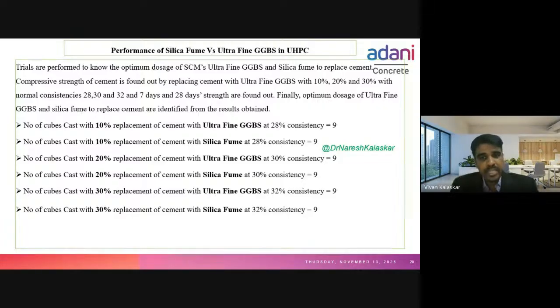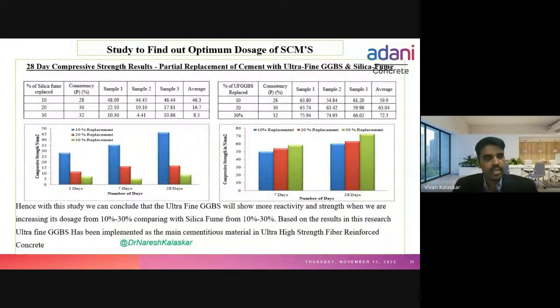We have replaced the cement with ultrafine GGBS and silica fume at 10%, 20%, and 30%. After mixing, we cast mortar cubes and tested them at 3 days, 7 days, and 28 days. These are the results we got. When we added 10% silica fume, we got 46 MPa compressive strength. When we increased the silica fume to 20%, the 28-day compressive strength drastically went down, to around 16.7 MPa.